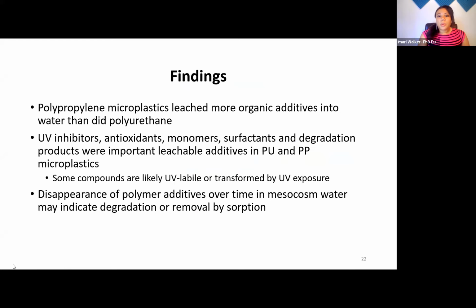Just that polypropylene microplastics definitely demonstrated that they had more organic additives available to them than the polyurethane for this material in particular. And there were quite a few different compound classes that were present that were important and leachable within both of these microplastics. And finally, there was a trend of disappearance of these microplastics over time, especially within the mesocosm itself. And so that indicates that there are just different phenomena that you can see when doing a benchtop experiment versus actually doing an environmental study of these compounds.